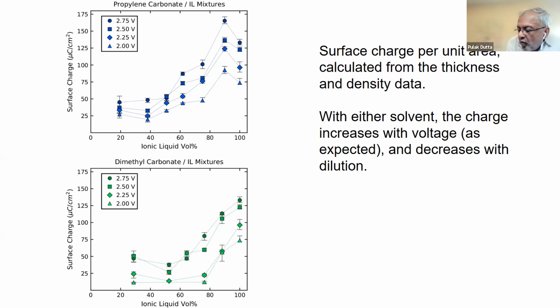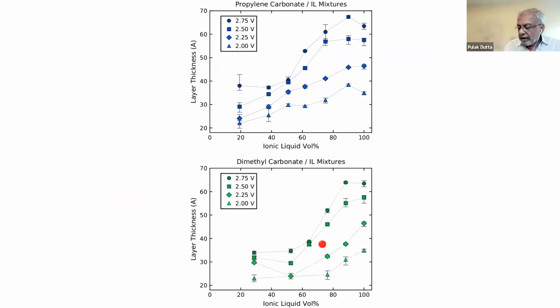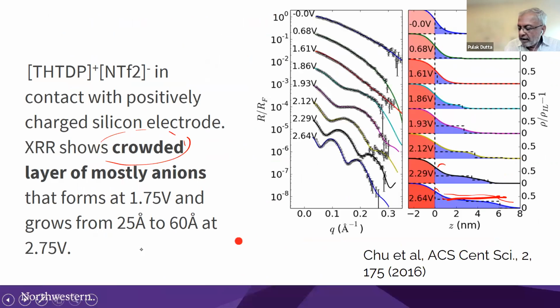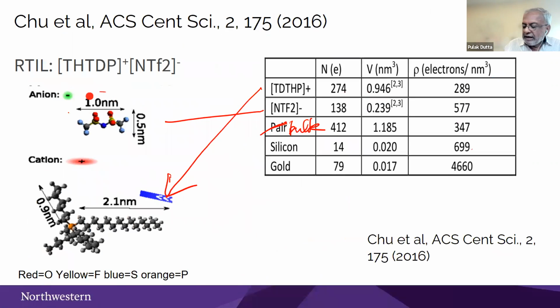So what's happening here? Well, there's one of the many things we don't know, going back to the double humped form of the capacitance that people measure. We can't go to the other hump, because if you change the sign of the charge, instead of anions, you attract cations, and cations don't have any contrast with the bulk. The difference between this density and the bulk density is much smaller.